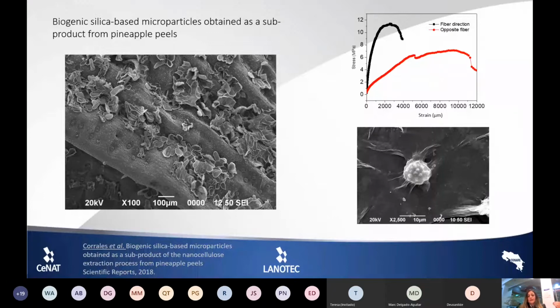So we started, if you see the microscopy here that I'm pointing out, we started analyzing initially the raw material. Once we saw it in the microscope, we could see all these small, from here in this microscopy, looks like dots. They are well patterned, aligned all along the shell of the pineapple. And we started to analyze its composition. These small dots are finally rosettes of biogenic silica. They are well patterned and well formed by the plant.